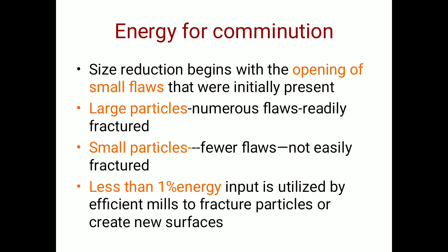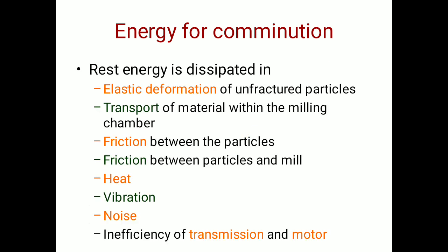It is a fact that less than 1% of the energy input is utilized by efficient mills to fracture the particles or to create new surfaces. So the rest of the energy is dissipated in elastic deformation of the unfractured particle, or transport of material within the milling chamber from one place to another, then friction between the particles, and not only that, friction between the particles and the mill, heat, vibration, noise and inefficiency of transmission and motor.